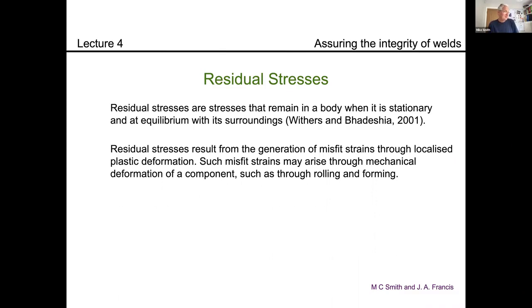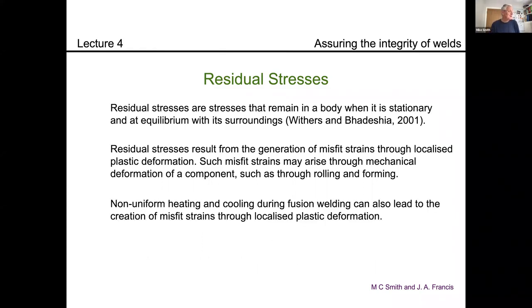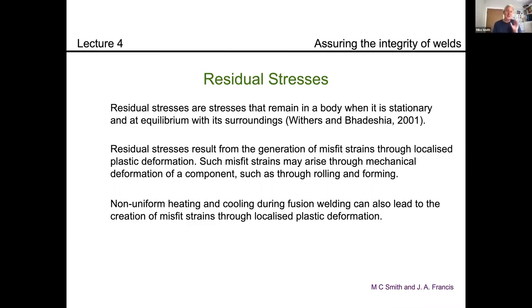Residual stresses are caused by what we call misfit strains — localised plastic deformation. They can arise through mechanical deformation such as rolling or forming, or due to non-uniform heating or cooling during fusion welding. What happens is you stretch one part of the component plastically — you get loads above yield in one part so it permanently deforms. When you take the loads off, that part of the component no longer fits into the space it originally occupied, and it's squashed or pulled by the surrounding material. You set up an elastic stress field due to plastic misfit strains.